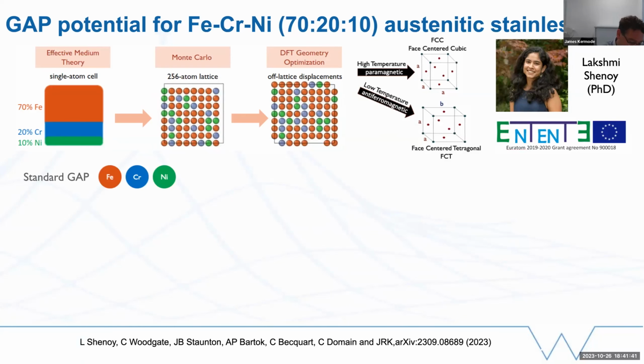And what Lakshmi has done very recently actually is to expand that a little bit. And we've taken a fairly simple approximation where we're using 2 different species to represent the upspin and the downspin information. So we're not fully describing the magnetic response. We're describing it in an approximate way where we're saying half of the atoms are upspin and half of them are downspin. We're taking this information from the magnetic moments in the DFT calculation as additional input, but we're not fully describing the magnetic response. We're just categorizing it. So it's a categorical variable rather than a continuous variable describing the spin.